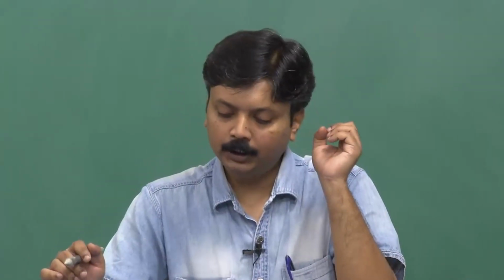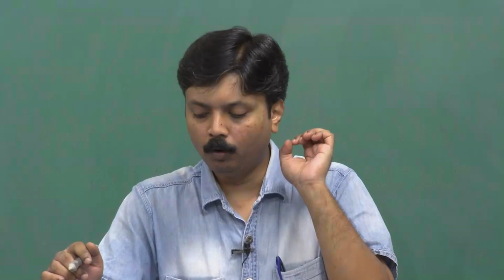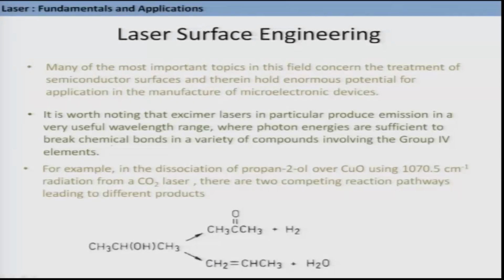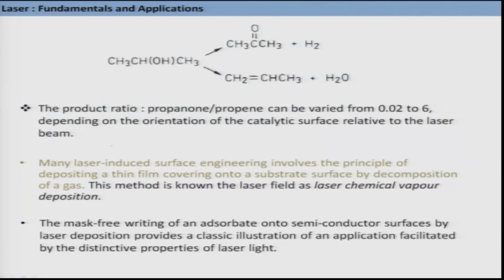For example, in the dissociation of propan-2-ol over copper oxide using 1070.5 centimeter inverse radiation from a carbon dioxide laser, there are two competing reaction pathways leading to different products. One is propanone, another is propene. So, the product ratio of propanone to propene can be varied from 0.02 to 6 depending on the orientation of the catalytic surface with respect to the laser beam.